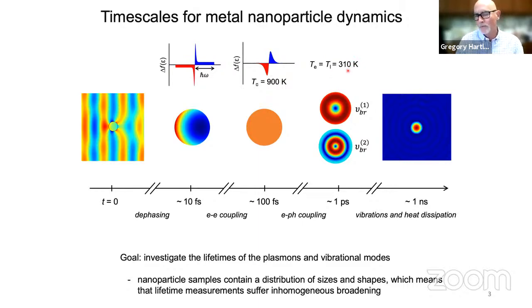So when you heat up a metal, heat the lattice, it will want to expand, right? Everything wants to expand when you heat it up. And because the heating process is so quick, it's almost invariably faster than the coordinates or the vibrational modes that correspond with the expansion process. So these are the breathing modes of the particle. And this is a situation where you can coherently excite these breathing modes. That's one of the major things that we see in the experiment. And this is, again, a cartoon of some breathing modes in COMSOL. And then those modes will lose energy into the environment, right, by coupling to whatever they're around.